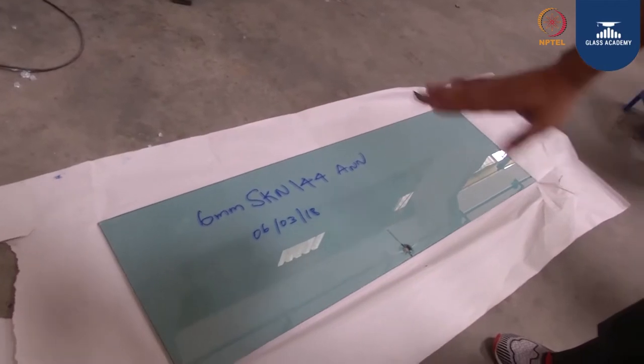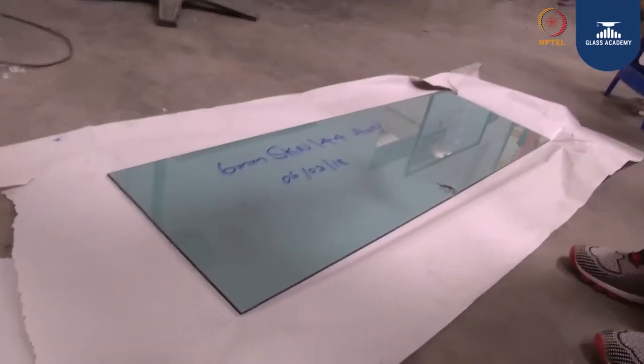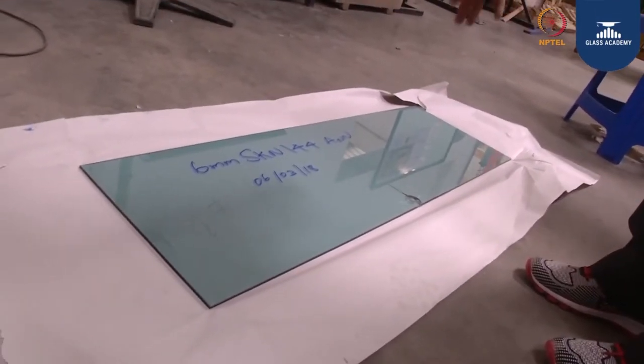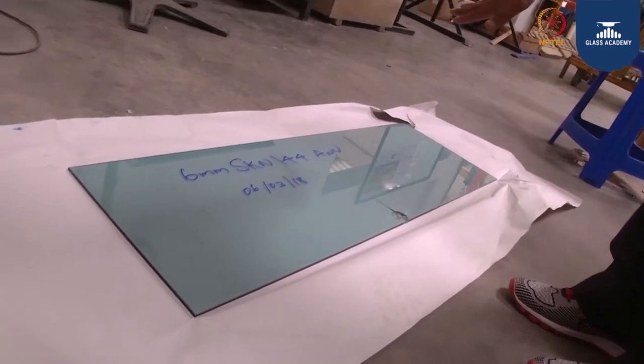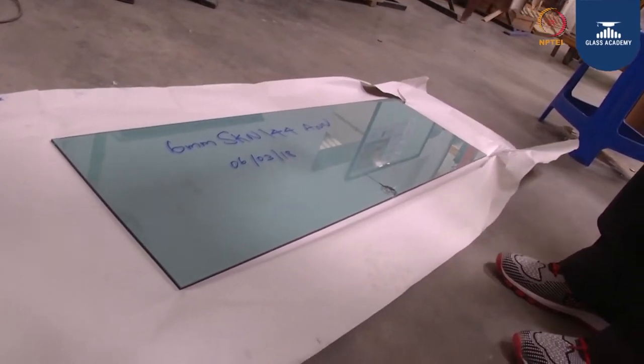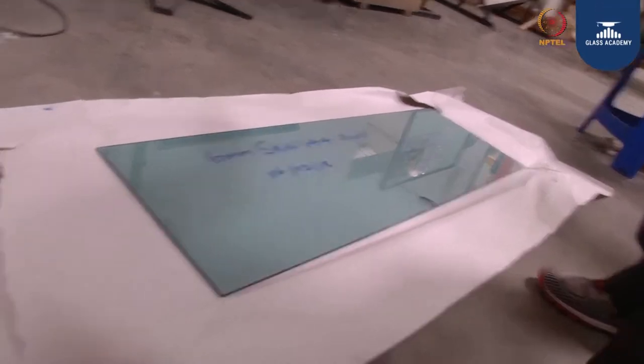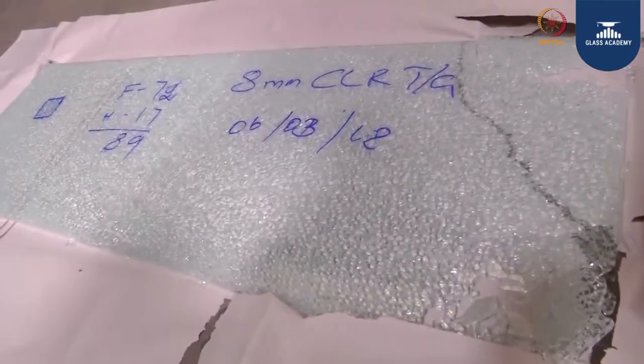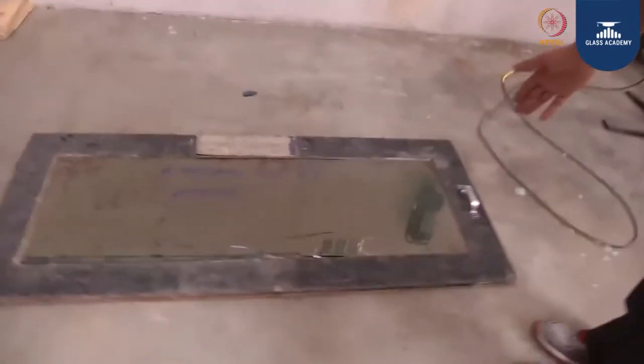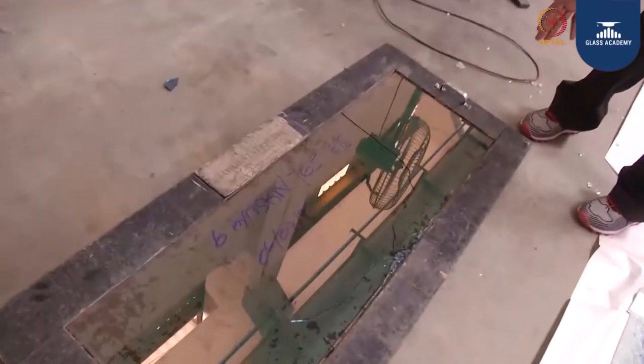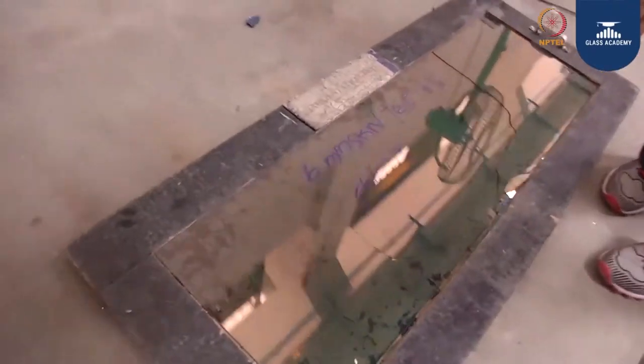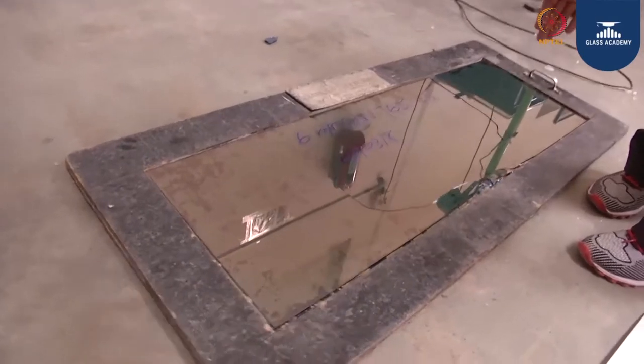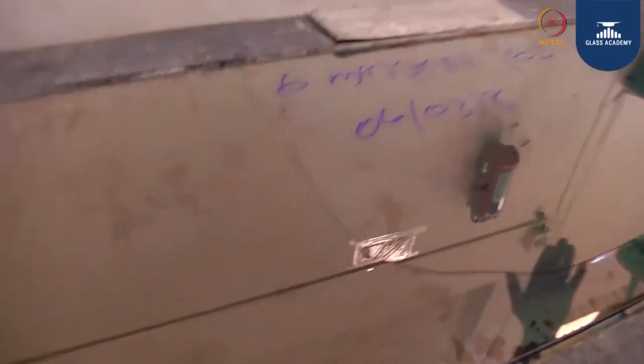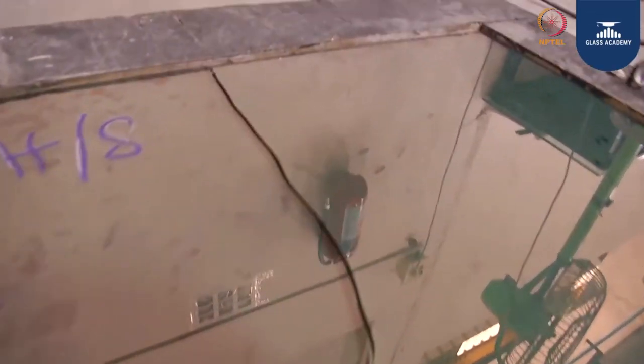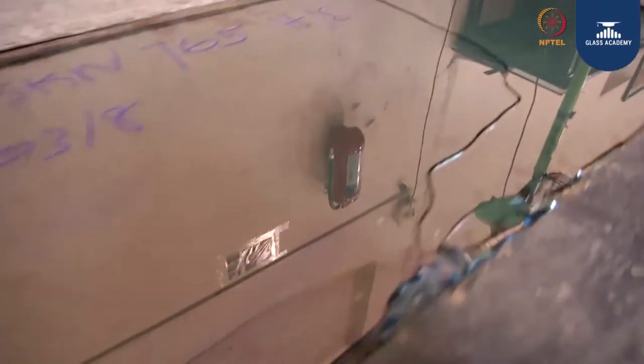If I break an annealed glass, it has no direction, it has no pattern. It can break in irregular pattern and it can create injuries also. So annealed glass will break like this. Whereas if you see a heat strengthened glass, from the impact point, the crack will end at the opposite edge, which describes it is a heat strengthened glass.